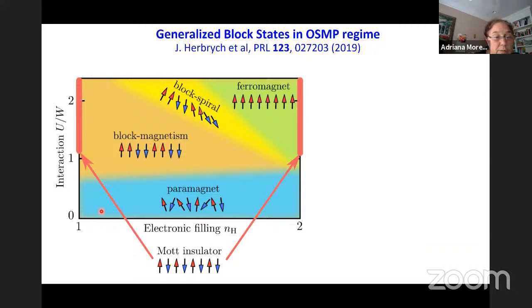So we see that there is at low U, for all dopings, we have a paramagnet. As U increases, we get a Mott insulator at both integer fillings, which is this peak at pi that I already showed you in S of Q.